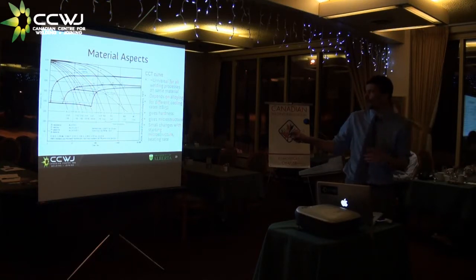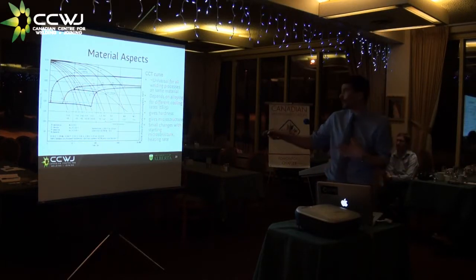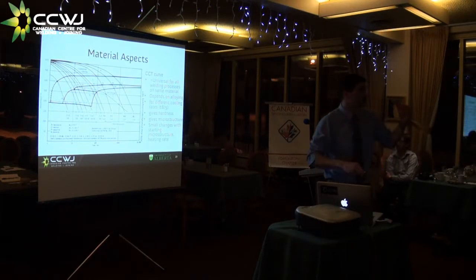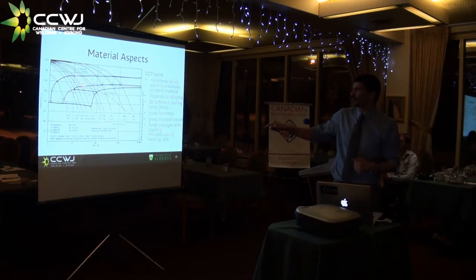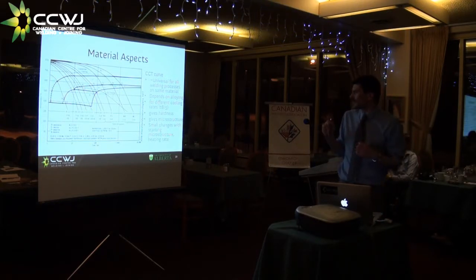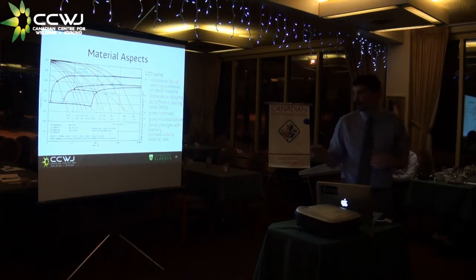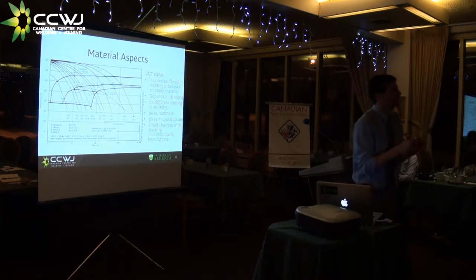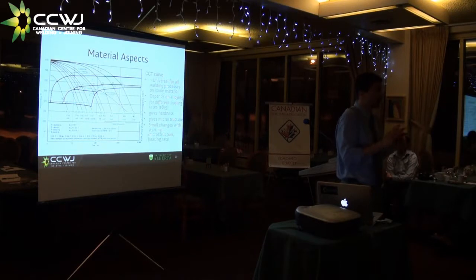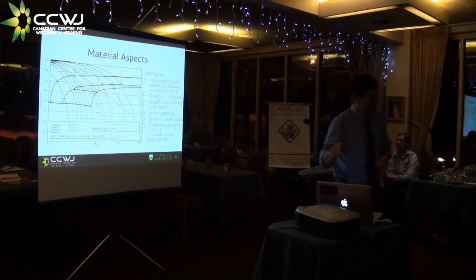Now, this graph is made for different cooling rates. So different Δt8/5s, as if we had different heat inputs or different preheats, right? These curves are awesome. They give us hardness for a given cooling rate. They give us what microstructure we're going to have, like if it is 76% primary ferrite, 16% pearlite, 6% bainite. These curves tell us this. Small changes, and these curves are not absolutely universal, because if I have a different heating rate to get to this hot temperature, or a different starting microstructure, they might vary a bit. Some people might argue that it's a little bit more than a bit. But again, when we compare with absolute ignorance, with not knowing anything, saying, Joe, weld this, these curves talk to us. They can help us make sense of many things.